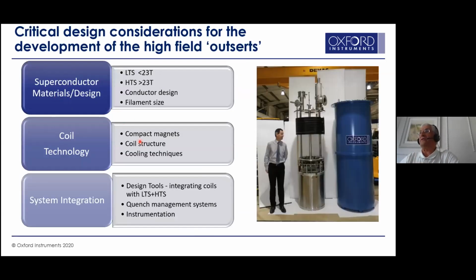So there are three critical elements required in developing high field systems: the superconducting materials and their design. If you are dealing with less than 23 Tesla, then you can rely on LTS material. If you have to go higher, you have to start thinking about HTS. And so far, Oxford involvement is really in the R&D stage, in the prototyping, not in the product stage. The next phase is looking at the engineering and the coil technology required. If it's compact, it will require certain engineering requirements versus coil structure and the cooling techniques.